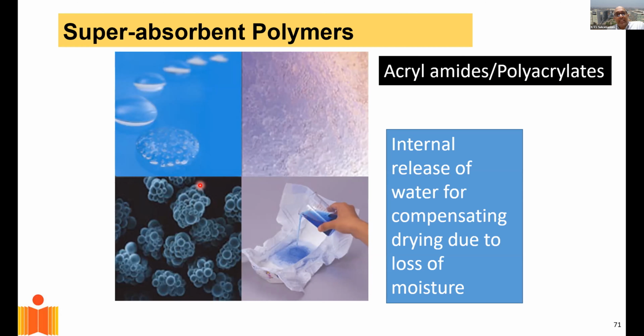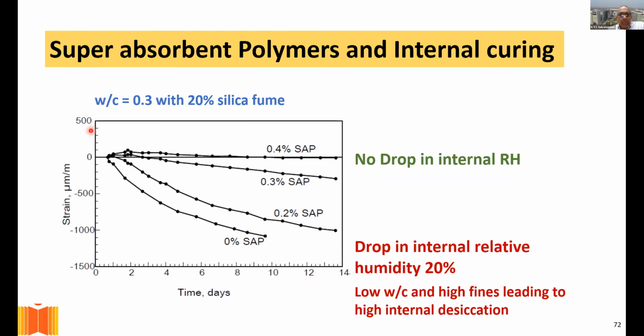basically reduces the shrinkage. Just to show you, if I don't have SAP in this densified concrete, I'll get a lot of shrinkage. By adding just 0.4% SAP, I'm able to completely eliminate the shrinkage. So you can see that there's no strain in the concrete. So concrete does not shrink. So these are all things that are now happening on the material front that help us address the issue of cracking in concrete, making concrete more durable.